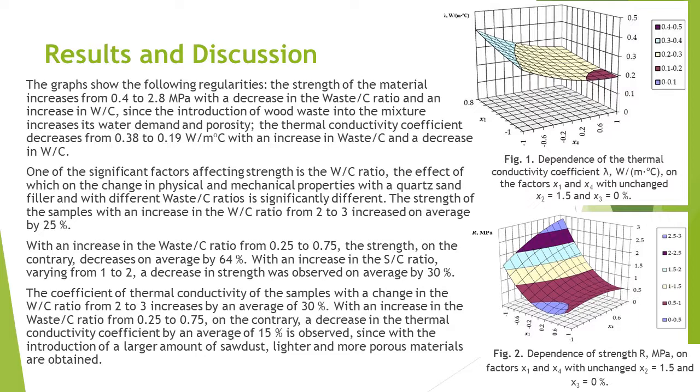With an increase in the waste-cement ratio from 0.25 to 0.75, the strength, on the contrary, decreases on average by 64%. With an increase in the sand-cement ratio from 1 to 2, a decrease in strength was observed